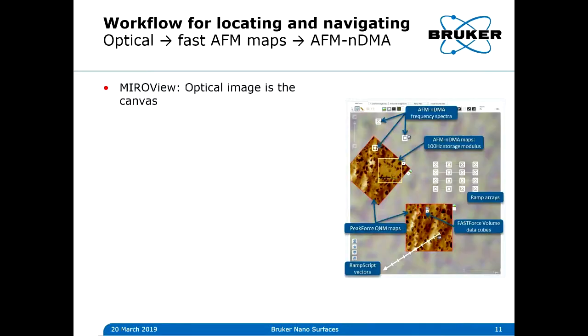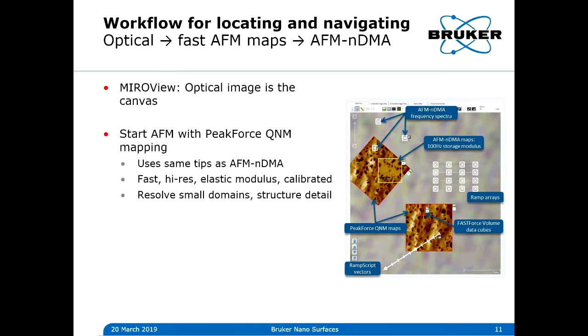When using the Dimension Icon with AFM-nDMA, the workflow goes as follows. The first step is pretty much the same as what you'd work with if you worked with an Icon before. You just navigate to the area of interest using the Icon motorized stage and the optics. Then you engage and scan with PeakForce QNM mechanical mapping. That gives you a fast, high-resolution mechanical property map and allows you to choose locations for doing your co-located nano-DMA